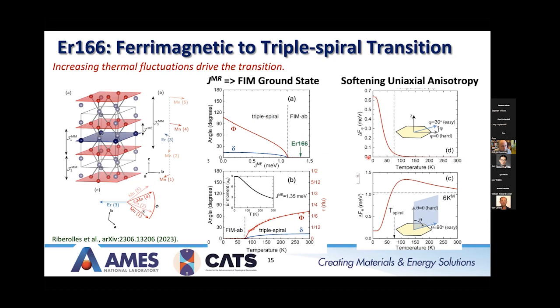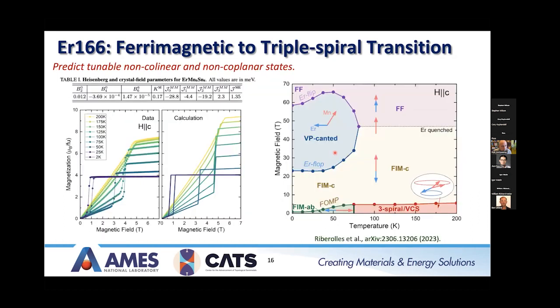You get this transition from the ferrimagnetic state into the spiral state. All right, so this next graph here, we're looking at some magnetization data taken at Ames. We're comparing that to the same data using our model parameters from our calculation. Again, in the ferrimagnetic state, you see this sharp step, which corresponds to what we call a FOMP, first order